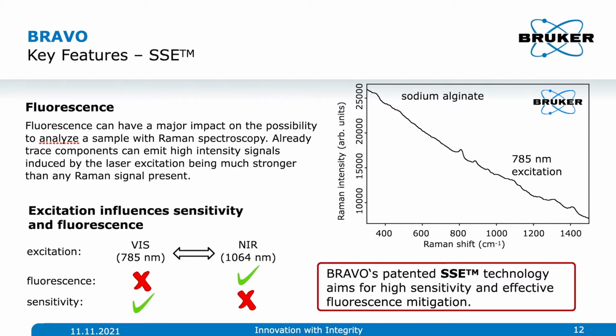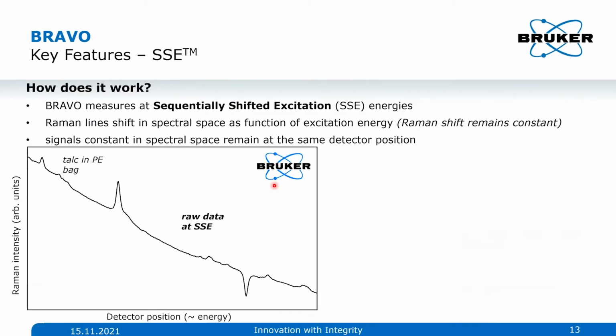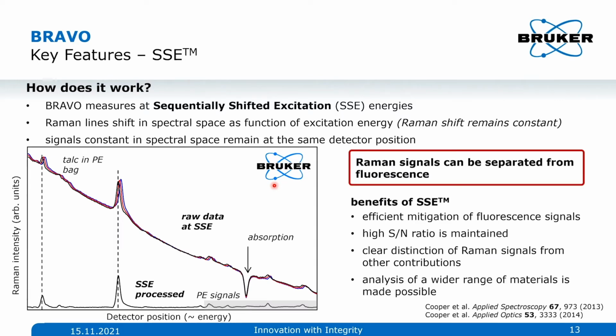Other features I mentioned before, we actively shift the laser 3 times each laser, and that enables us to get rid of the fluorescence and maintain sensitivity that you wouldn't have if you tried to move to even longer wavelengths at 1064. So here's a good example looking at talc in polyethylene bags. And you can see we shift the laser 3 times, and now we can divide off the fluorescence and any absorptions that you might have and get a perfect spectrum of the talc. This is really unique to any handheld system, to be able to collect this quality data with getting rid of the fluorescence so efficiently.